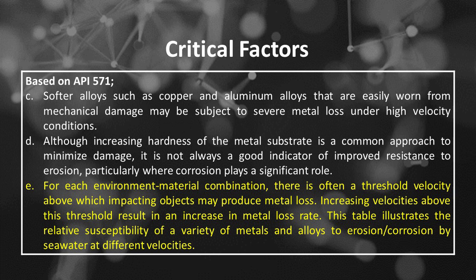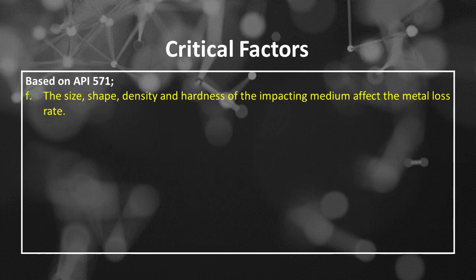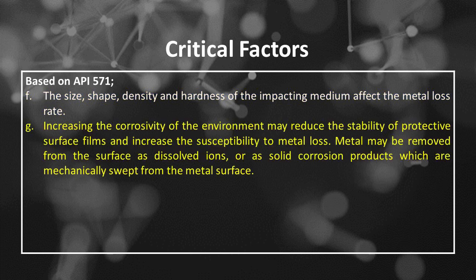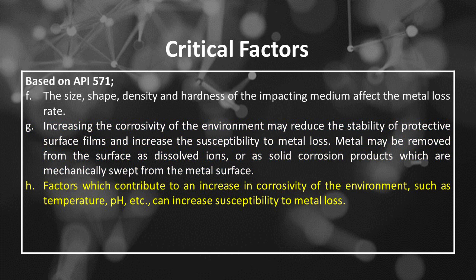This table illustrates the relative susceptibility of a variety of metals and alloys to erosion/corrosion by seawater at different velocities. The sixth is the size, shape, density and hardness of the impacting medium affect the metal loss rate. The seventh is increasing the corrosivity of the environment may reduce the stability of protective surface films and increase the susceptibility to metal loss. Metal may be removed from the surface as dissolved ions, or as solid corrosion products which are mechanically swept from the metal surface. The eighth is factors which contribute to an increase in corrosivity of the environment, such as temperature, pH, etc., can increase susceptibility to metal loss.